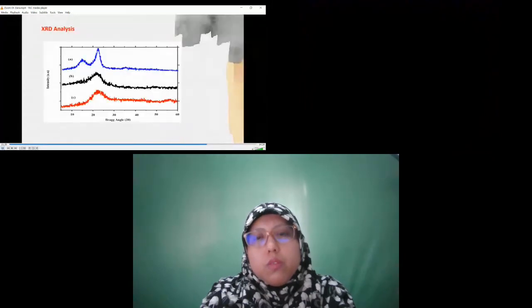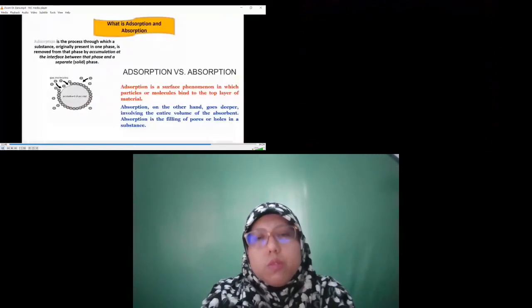This is our XRD analysis. We can see P is our char and C is our carbon. Both of them are amorphous. That's why the peak is blunt. But A is our biomass, which has cellulose, and cellulose has amorphous and crystalline peaks. So that's why there are 2 peaks.